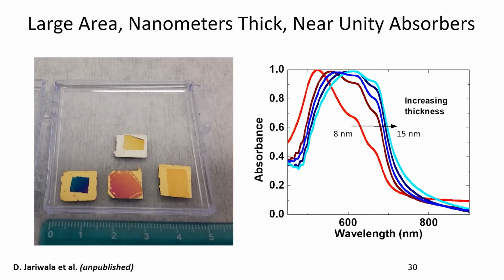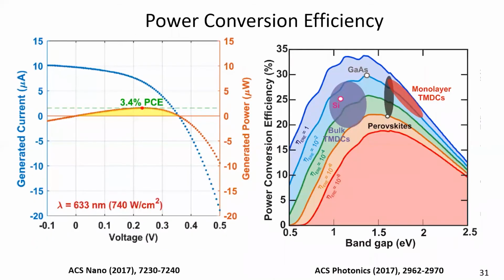Certainly there is room for scaling this up. The question is, where do we go with this? So the dirty secret is out here. The power conversion efficiency is still not very large. It's about 3 to 4%. Okay, and this is not great. But for the thickness that we have, for a lot of these space-based applications, this may be enough if you just normalize it to the weight.